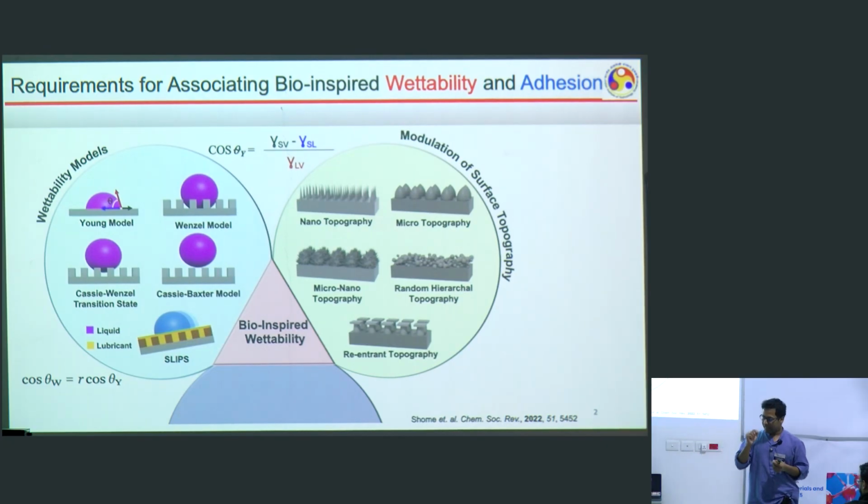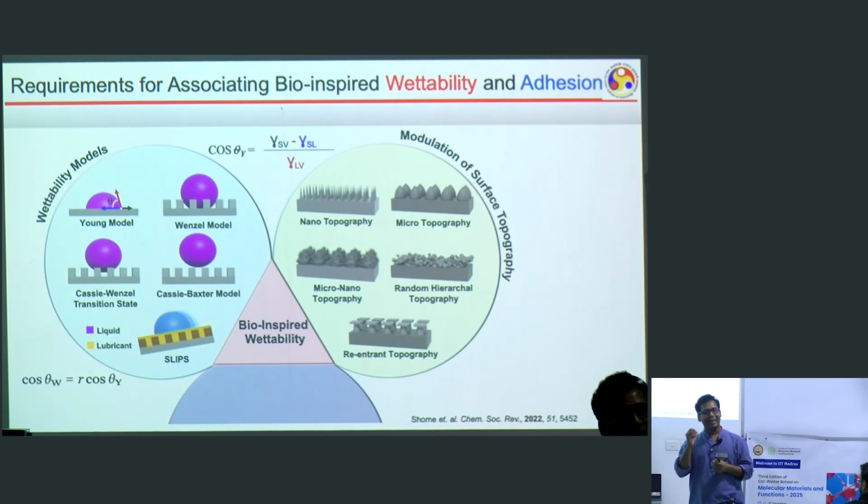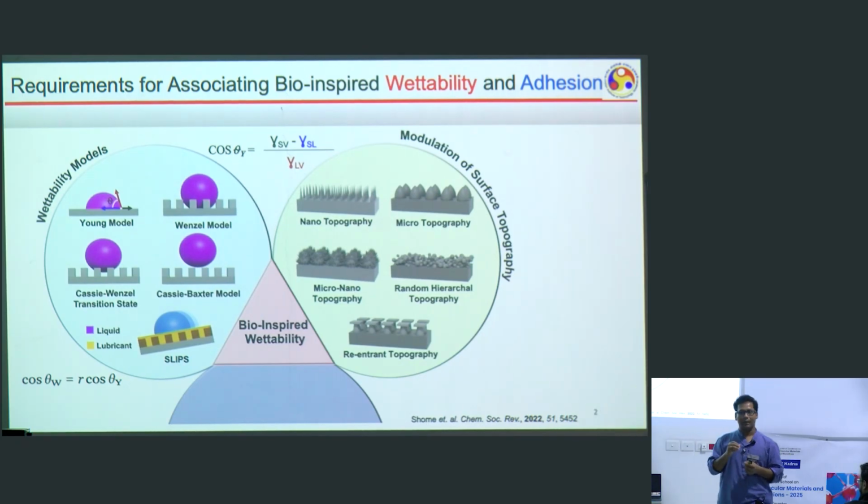So it's basically for super hydrophobic interfaces like the lotus leaf. There, the entrapped air in very rough interfaces, or say interfaces which have a dual degree of roughness, I'll talk about that in a little more detail. In the grooves, there is entrapped air which minimizes the contact between the liquid and solid interface. Because of that, you see this heterogeneous liquid wettability and extreme repellence.